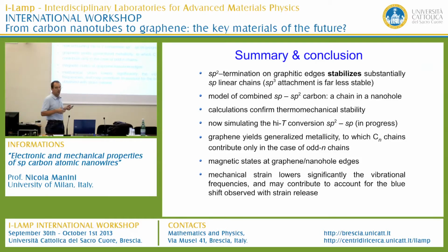Of course, this is just a model. We don't expect there is exactly that specific hole. There could be a very much more complicated situation, but it just gives an idea of what can be going on in these samples. Indeed, the calculations confirm thermomechanical stability of those chains, which can be kept for weeks as long as they're in vacuum, and they remain stable.